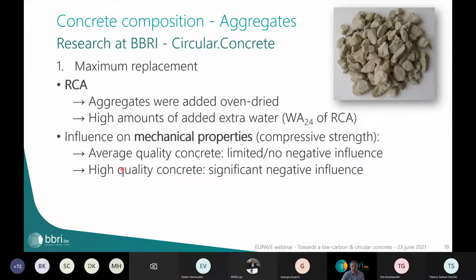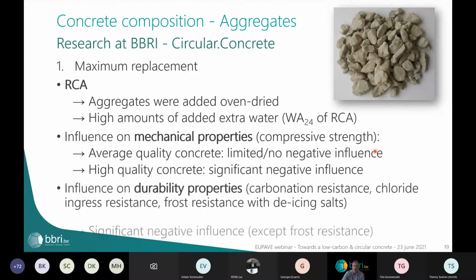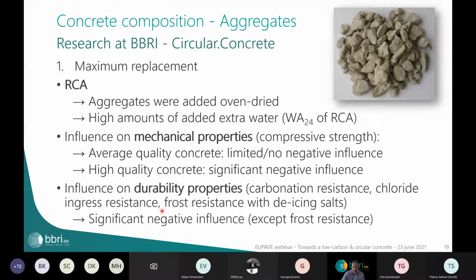Only when we looked at the high quality concretes, there the influence was immediately visible and very significant. This is also the reason why the standard at the moment limits it at very small percentages. But you do not have to go to 100% of replacement always, but a higher percentage than what the standard says is certainly possible.